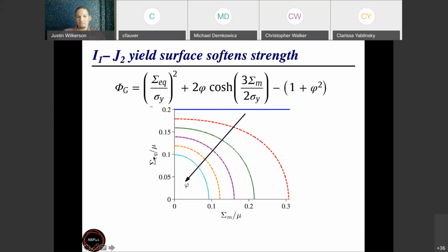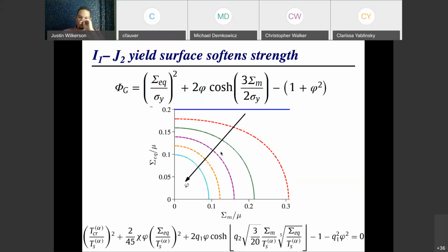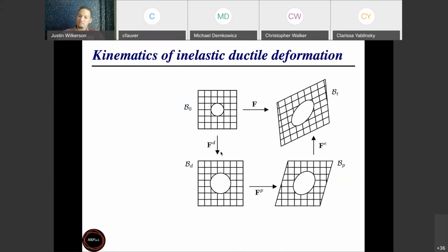On the y-axis I have the maximum von Mises stress that you can apply to this material before it will start inelastically deforming. And on the horizontal axis, I have the maximum mean or hydrostatic stress that you can apply before this will start to inelastically deform. And then you can see how these curves depend on the porosity itself. If I'm inside these curves, then I'm elastically deforming. If I'm on the outside of those curves, then I'm inelastically deforming the material. And then we can build out more sophisticated versions of this for crystal plasticity.